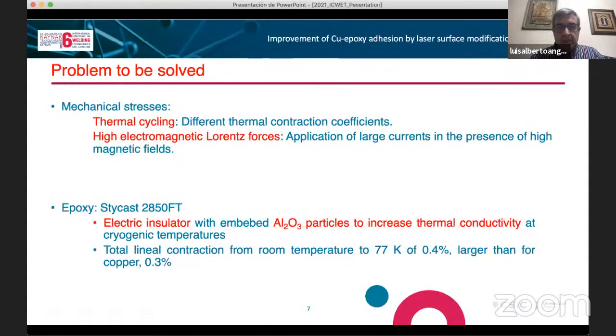Okay. So which are the problems that these joints can have to deal with? The first one is mechanical stresses due to the thermal cycling, because you have materials with different thermal contraction coefficients. After, you have high electromagnetic Lorentz forces because you are applying large electrical currents in the presence of high magnetic fields. And why did we select the Stycast 2850FT?